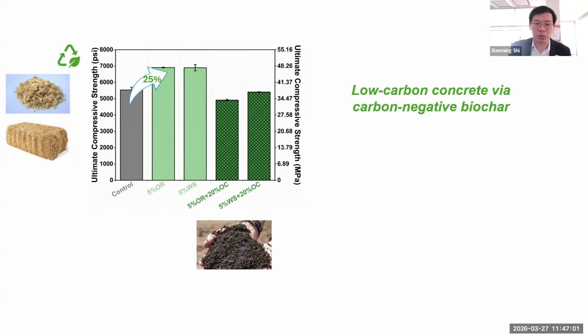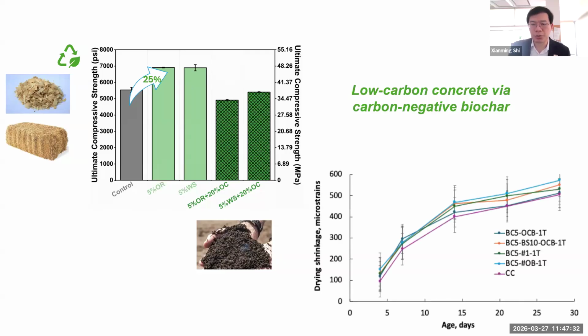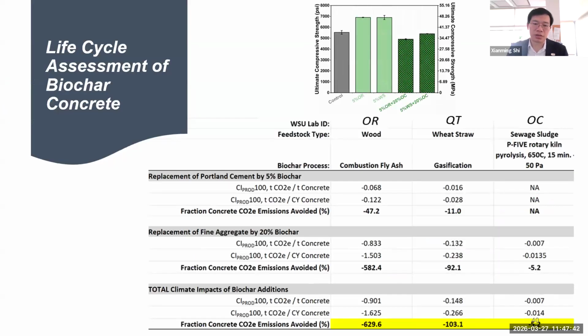So what if we add even more biochar? Then we achieve, in this group, again, replacing 20% of sand with the weathered biosolids derived biochar, comparable, slightly lower strength, but that's typically sufficient, especially for pavement applications. But then we may be able to incorporate a lot more CO2, gain a lot more carbon credit, and also divert more waste streams towards beneficial use. So, drying shrinkage-wise, it's different than what we saw in the other study. We are seeing slightly increased shrinkage because, well, every product is different, I guess.